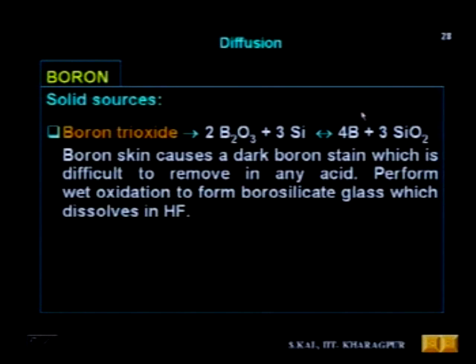and the boron atom will diffuse into silicon. Now, during this reaction, a boron skin will form, which is also known as boron stain, and it will be deposited on silicon. That particular stain is very difficult to remove in any acid, and for that we have to perform a separate step, which is known as low temperature oxidation or LTO. Before driving, we have to remove that stain, otherwise that stain will act as a continuous source of dopant.